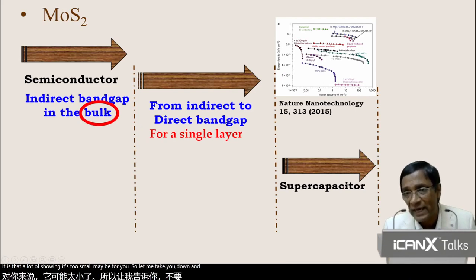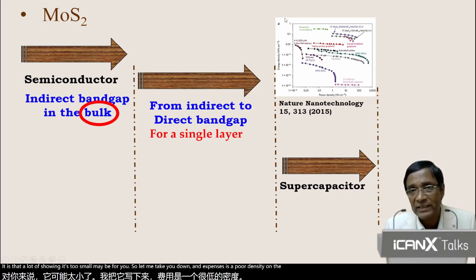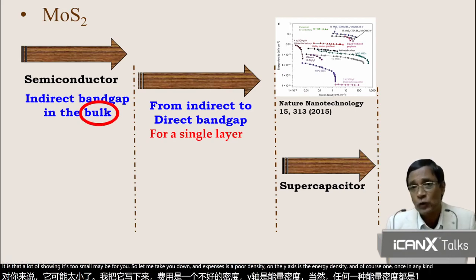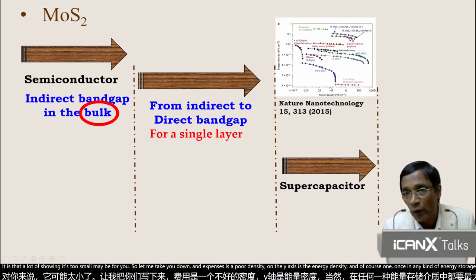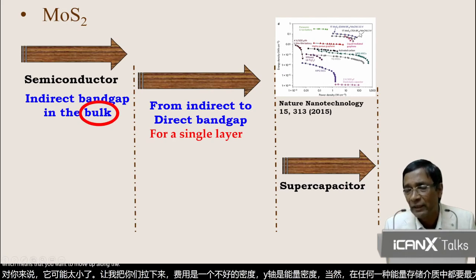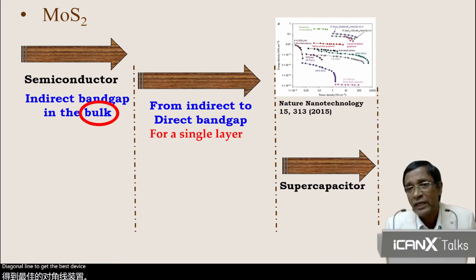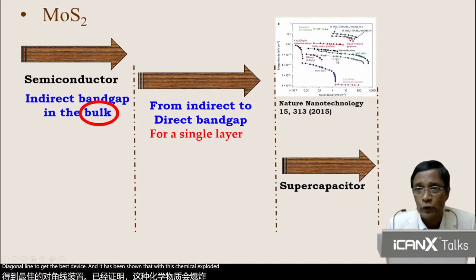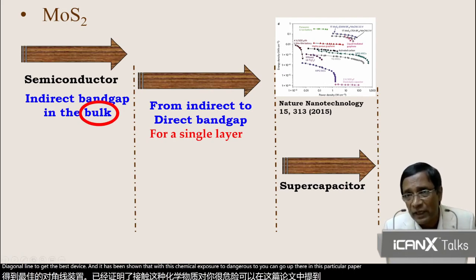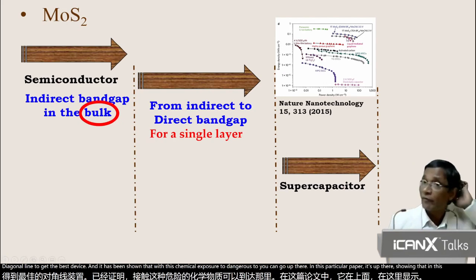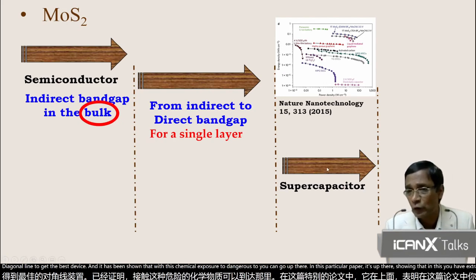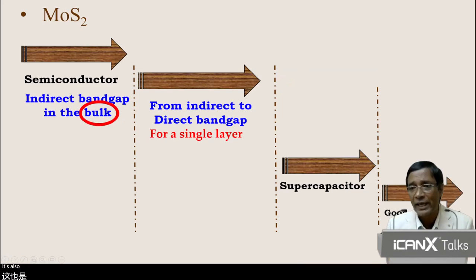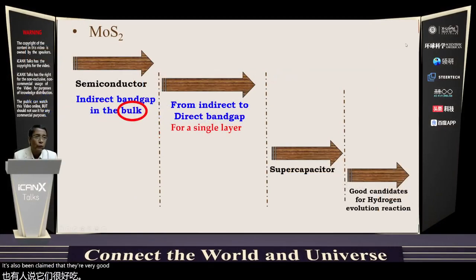Here is a plot, it's too small maybe for you, so let me read it out. The x-axis is the power density. On the y-axis is the energy density. And of course, in any kind of energy storage material, one wants to maximize both power density and energy density, which means that you want to move up along the diagonal line to get the best device. It has been shown that with this chemically exfoliated MoS2, you can go up there in this particular paper, showing that you have extraordinary properties of MoS2. It's also been claimed that they are very good for hydrogen evolution reactions.